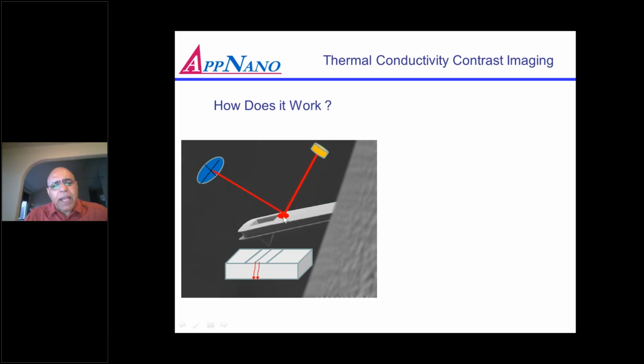So for normal applications in a temperature contrast mode, you keep the laser away, or you're scanning or doing topography, you don't need to move it closer to the thermocouple, which can still work from here. But when you want to move into the thermal conductivity contrast imaging, then you move the laser closer to the pit, so that half of the laser is on the pit, half of the laser is on the flat surface, and it's half of the laser on the flat surface that is enough to get a good sum signal.